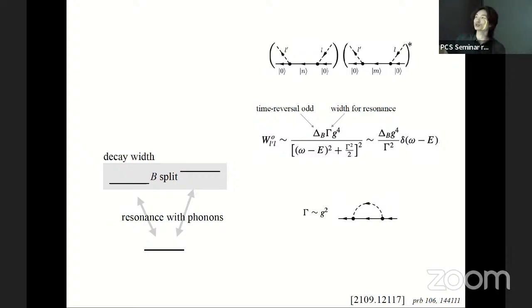And it should also be proportional to the width of the resonance, because only for phonons within the range of the width can have resonance scattering. And it should be proportional to the coupling constant to the fourth power, because in the calculation of the amplitude, the phonon needs to be absorbed first and then emitted. Right, and then you take the square to get the probability, so you have G to the fourth. And also the intermediate state has its own Green's function, and because you take the square, it has a square. And it will be approximated like something like this.